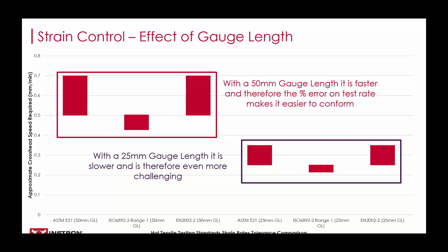Now, if you're in a position where you use a 25 millimeter gauge length specimen, but you're not equipped to do closed loop strain control, the standard does allow using crosshead displacement control, as long as you choose a speed that results in a conforming strain rate at the determination of yield properties. As illustrated here, that can be tricky. Beginning of the test.